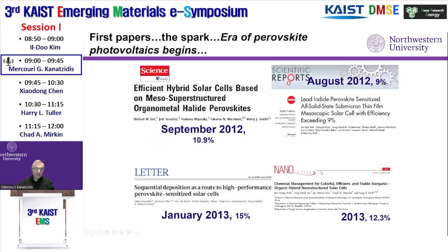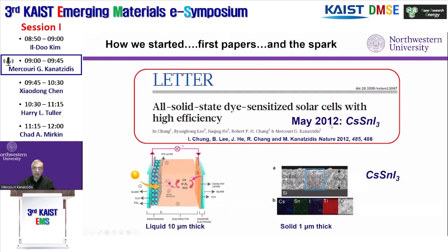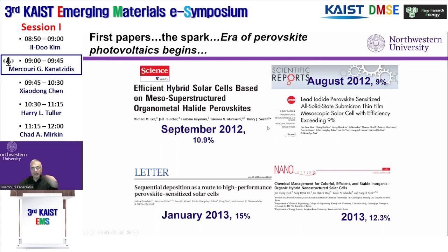Now, as time went on, in August and September of 2012, two more papers came out. One was from Korea, from Nam-Gyu Park, with his student. The first author is Hui-Seon Kim. And the second was from Henry Snaith and Tsutomu Miyasaka. These papers were submitted 2 weeks after our paper was published. And in fact, they cited our work in those papers. And they reported solid-state solar cells, using another perovskite they had, of 11% and 9%. And that also took the community by surprise. And then later, of course, others came in and reported the same cells with higher and higher efficiencies. And that started the whole field in 2012.